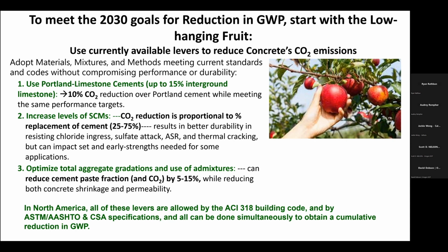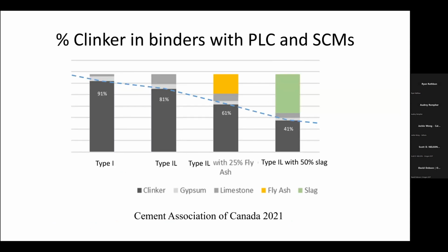These things are already allowed in the building code and in the various specifications, and they can be done simultaneously to bring down a cumulative reduction in global warming potential. As an example, if you use a type 1 cement, you've got 91% clinker in the binder. If you go to 1L, you're about 81. 1L with 25% ash, you're about 61, and 50% slag with 1L, you're down around 41% clinker, and since clinker is 90% of the CO2 emissions from concrete, that means you're having a significant impact on reducing CO2 emissions.